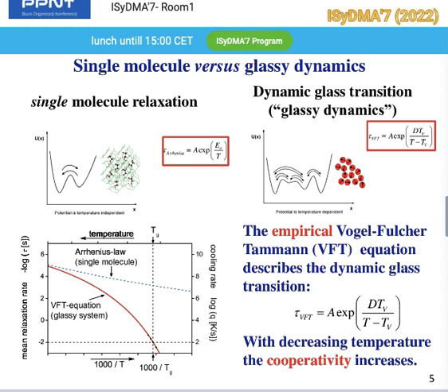This means that the activation energy for this glassy dynamics relaxation changes continuously with temperature. A possible explanation is that the length scale on which the relaxation processes take place increases with decreasing temperature. Typically one has at the calorimetric glass transition temperature a length scale of about a nanometer or perhaps 2 nanometers. It depends, of course, on the molecular system one is analyzing.